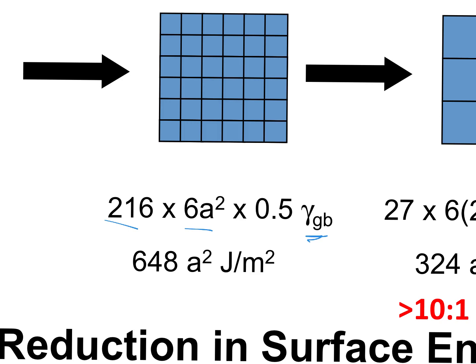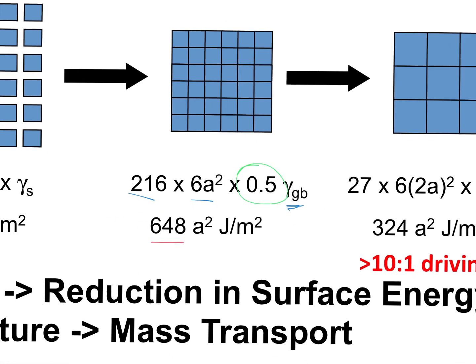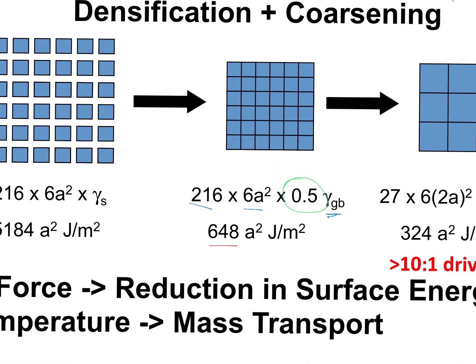Gamma sub s has been replaced by gamma GB. All right, so we made these grain boundaries by putting these cubes together, and we also have half the amount of surface area because now they're sharing those a squared areas. Okay. And so that in itself has allowed us to go from 5,184 to 648. So already we've dropped down the surface area quite a bit just by bringing them together and going from solid surface vapor interface to grain boundary interface, where two grains are looking at each other across this interface. And we've done no grain growth in this simulation. So there's a huge driving force just to get rid of surface. All right, that's what this is about.